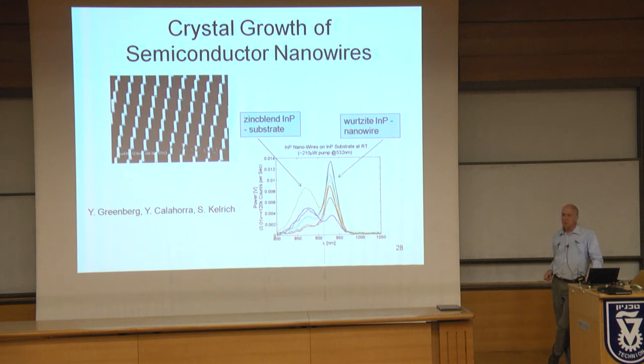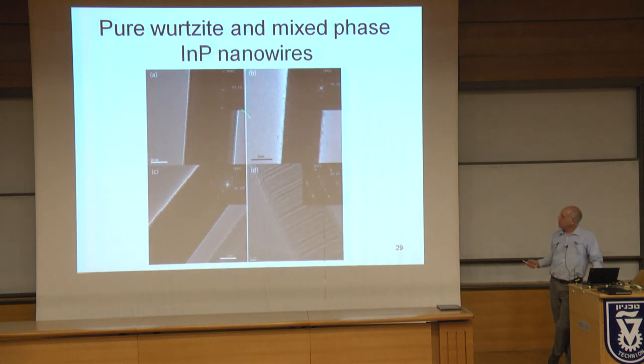It's not easy to grow these nanowires. We started this project 4 years ago and it turns out to be much more complicated than we initially thought. This is a VLS growth method where we have a gold particle on top of the nanowire, which is a catalyst for growth. Growth mechanism is very complex, not well understood, excellent subject for research. For application, the big question mark, but for research, very interesting. Some TEM pictures showing a pure wurtzite phase of the nanowires at a certain temperature. At other temperatures, we see a mixed wurtzite zinc blende phase at a higher temperature. That's what's happening.